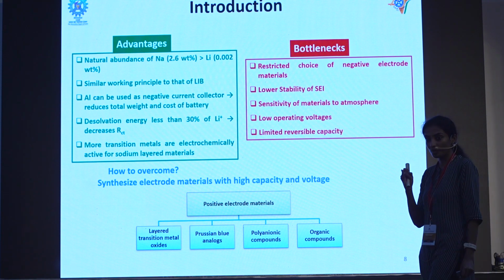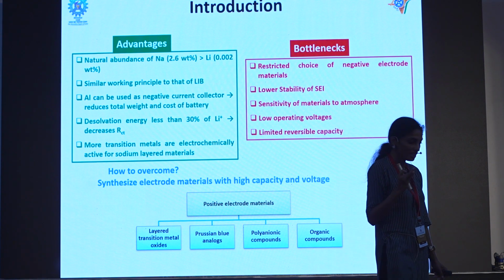The second generation of positive electrode materials, the Prussian blue analogues, suffer from difficulty in synthesis. We cannot synthesize Prussian blue analogues in a large quantity because the phase control is very difficult. So we have polyanionic compounds and Prussian blue analogues, and organic compounds are there just as miscellaneous because they have huge issues with high voltage stability. That is where the layered transition metal oxides are highly attractive, because they have a higher operating potential and a high capacity, and they are easy to synthesize on a large scale. It's an upscalable synthesis route.